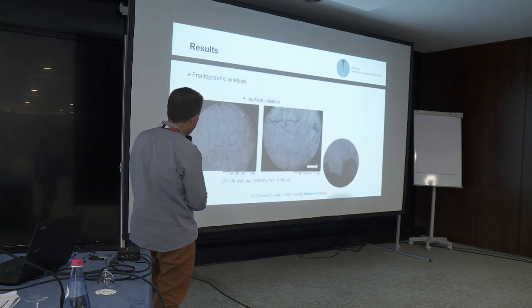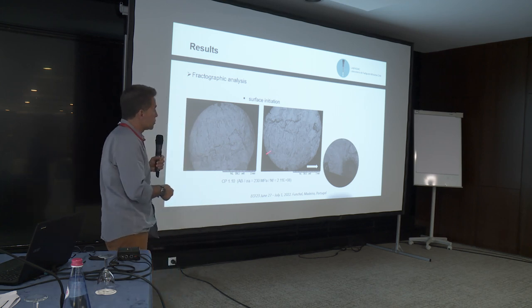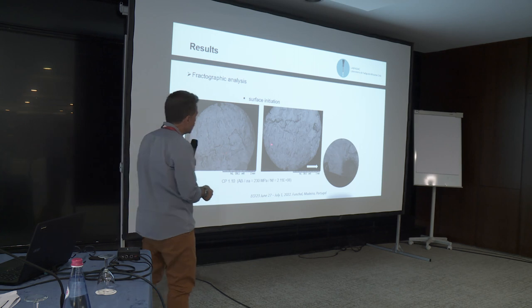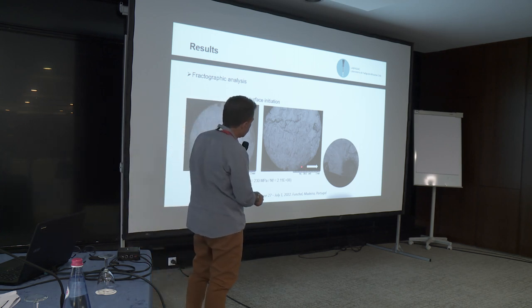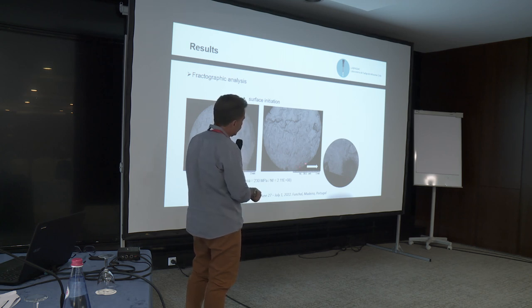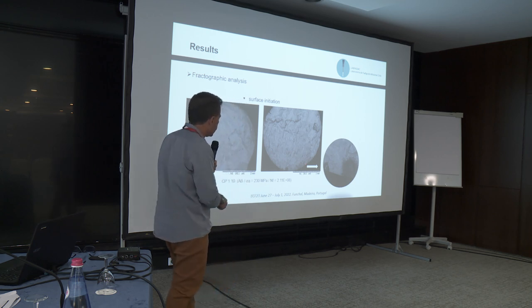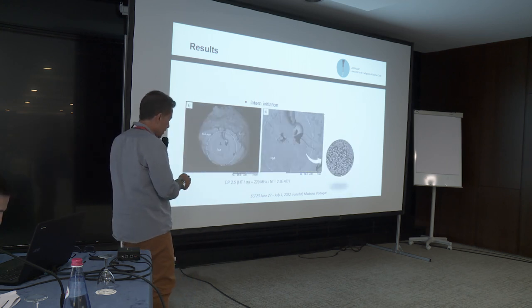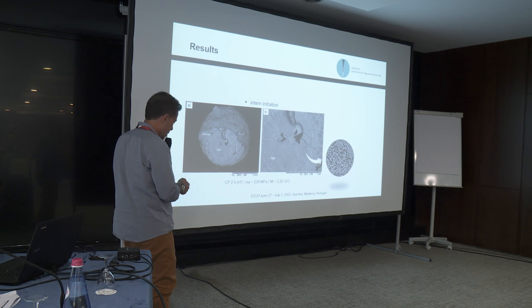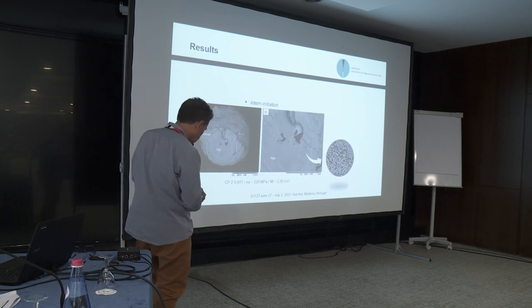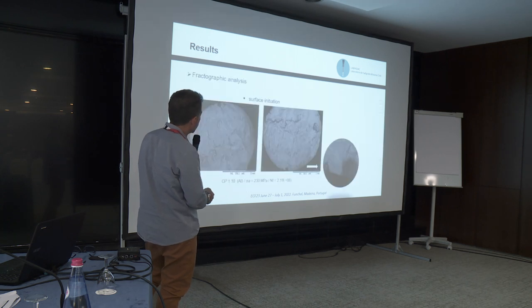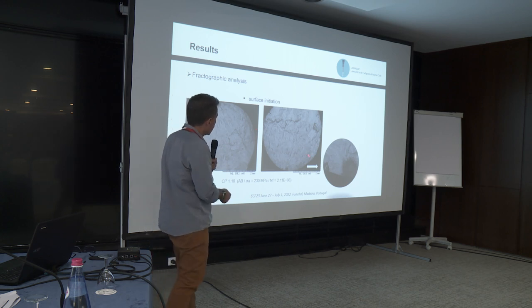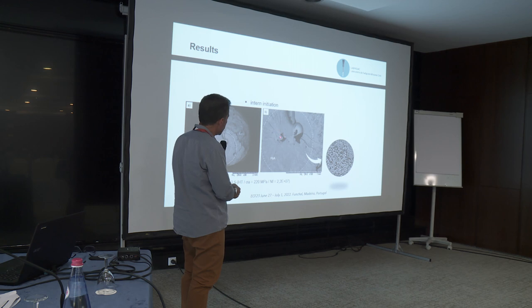Here we have some information about the aspect of the surface after testing. Here we have the initiation of the crack from a metallurgical defect, an inclusion exactly at the surface of the specimen. It was an as-built specimen. Then here we have surface initiation, and internal initiation also.